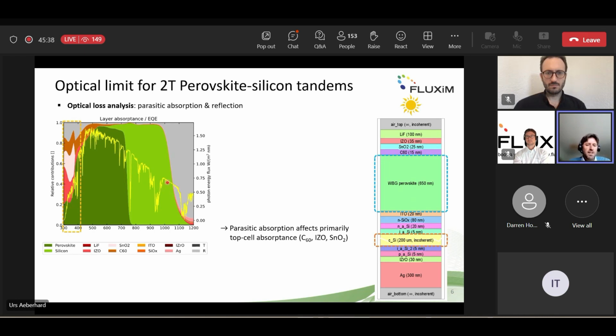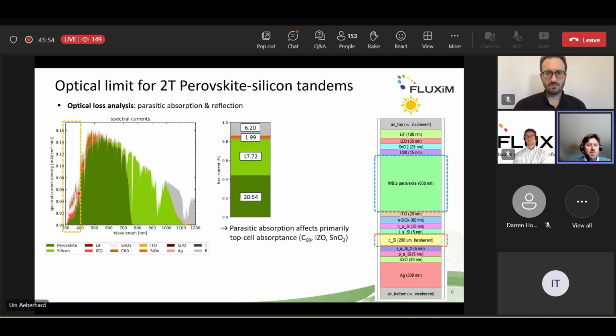However, we have to not only look at the absorptance, but most importantly at the photocurrent that is produced. And we see also that this parasitic absorptance is in a region where there's actually not too much photon flux. So another representation is then more useful that directly translates into the spectral current density. And so we can actually quantify the different currents, the one that is absorbed in the active layers and then the parasitic losses due to absorption in the non-active layers, and also the significant reflection loss that we still have here in the region of the bottom cell.